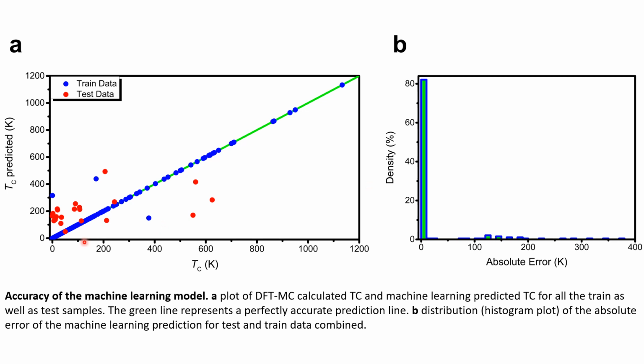So here are the results of our machine learning pipeline, which we have obtained using AutoML search of the model space as well as the hyperparameter space. These blue points are the training data points. You can see for training data, the model has fitted them beautifully, almost perfectly for most of the points, maybe a few outliers here and there. But for test data, the fitting is not very good. Actually, you can see a few points are pretty accurate, but for a lot of points, it's not accurate. The probable reason for this, we have speculated in our paper. Please go check it out.